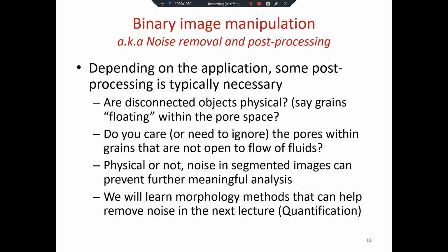So you might want to remove that from your simulation because it's going to affect the solid phases, affect the flow, and how the velocity profile looks, so you might want to remove those. Some care has to be exercised, but typically small noise can be removed. You're going to have a smoother ride as far as simulation goes. And you should make sure that the difference between your filtered image and your original is not huge.